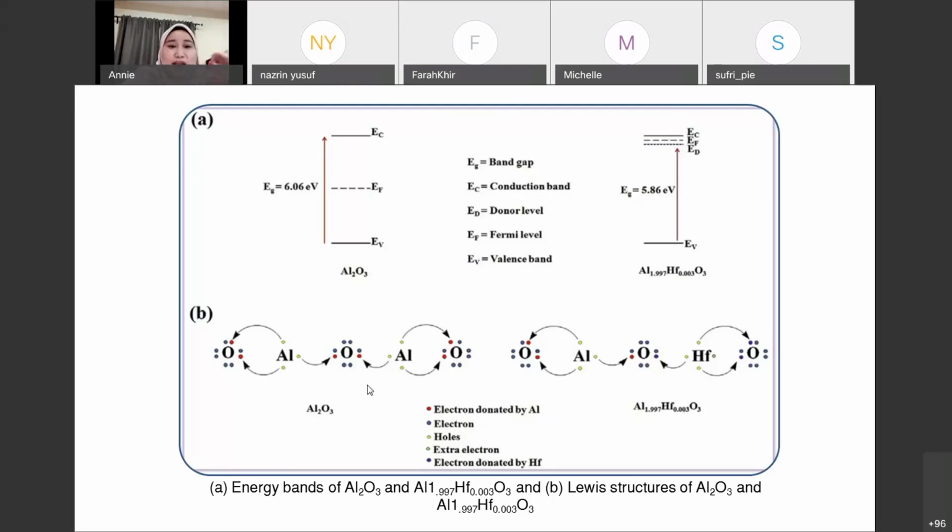Bear in mind that I am going to use aluminium oxide. I recognize aluminium oxide has a band gap of around 8.8 eV, but with that value of band gap, it has a lower K value. For your information, if you want to replace the existing oxide dielectric, which is silicon dioxide, and make sure your oxide is applicable in a very long-term period, we must at least have a K value of 12.